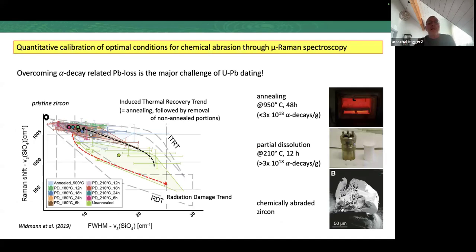So for this, we have to apply this chemical abrasion. It consists of 2 steps. First step is the annealing, 950 degrees, 48 hours. This is to anneal, to repair the parts of the grains which are at the first percolation point, so with damage less than 3 × 10^18 alpha decays per gram. And then we want to get rid of the rest, because we know that the rest has undergone a higher degree of damage and potentially has lost part of its radiogenic lead. So we do this using exactly the same acids we use for complete dissolution afterwards, just a bit shorter time. Same temperature, but shorter time. The complete dissolution will take something like 2 to 3 days, and our partial dissolution step is 10 to 12 hours.